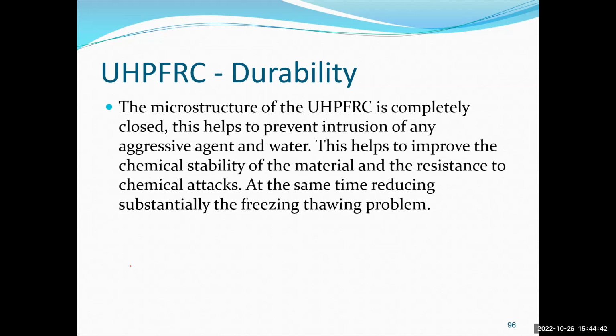So that's why the main purpose of the organic fiber is to absorb the steam that comes from the fire. So the microstructure of the ultra high performance fiber concrete is completely closed. So that means you do not need to use air content. You do not need the water to go through it. It's completely closed. Water does not penetrate into it. If it doesn't penetrate the water into it, then that means no freezing thawing problem. There's no excess water. There's no shrinkage. You think about that. This helps improve the chemical stability of the materials and resist any kind of chemical attack on the concrete.